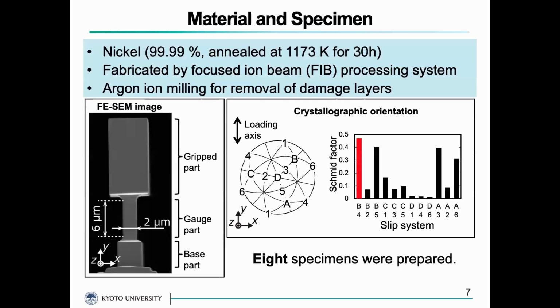We used pure nickel single crystal as a material, and the plate was annealed at 1173 Kelvin for 30 hours. The specimens were fabricated by a focused ion beam, FIB, processing system. The damage layers induced by FIB processing were removed using argon ion milling. The gauge part of the specimen has a square cross-sectional size of 2 micrometers and a height of 6 micrometers. Specimens were fabricated for a single slip system, the only slip system to be activated. Eight specimens with the same dimension and crystallographic orientation were prepared.